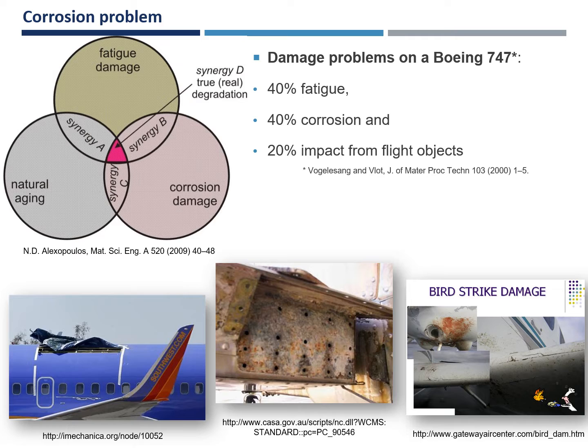According to research on a Boeing 747, it was found that approximately 40% of the damage problems are due to corrosion. The real degradation of the aircraft structures was found to be a synergy between fatigue damage, natural aging, as well as corrosion damage. However, in the present work, the synergy between aging and corrosion damage is investigated.